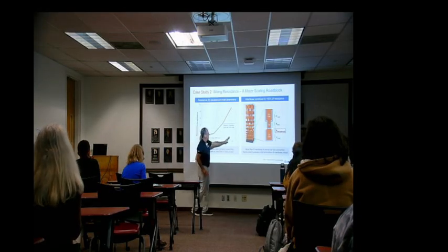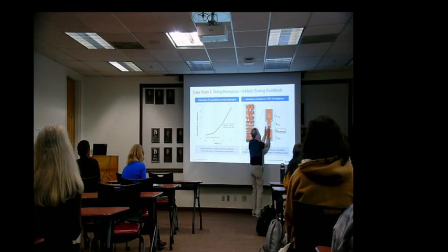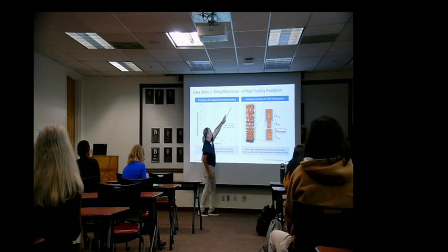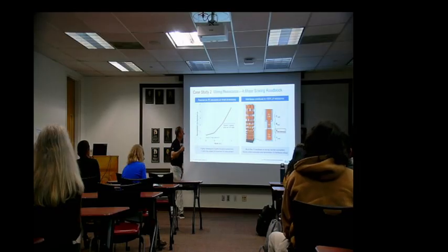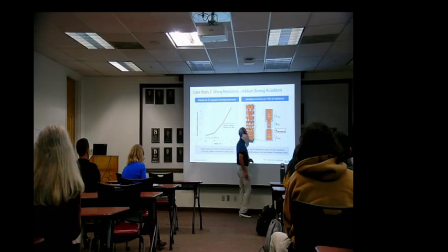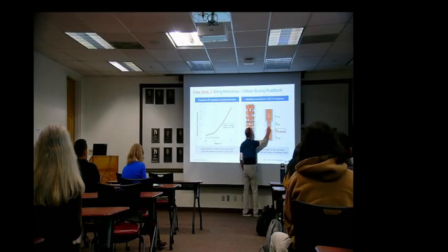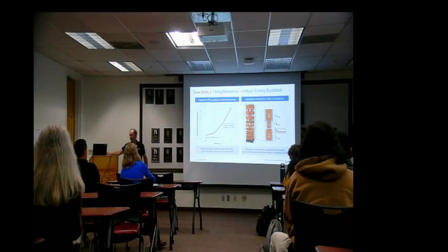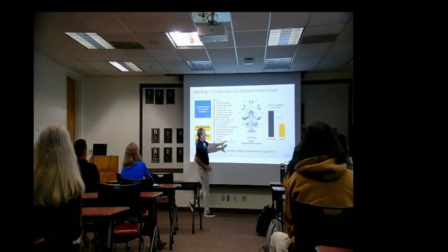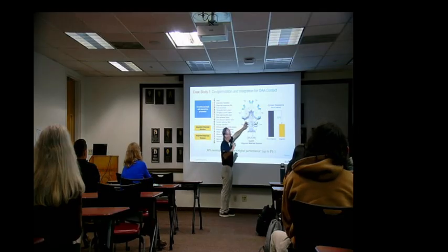So the problem is wiring resistance, and as you go to smaller nodes and the geometry gets smaller, the resistance of the line gets greater. We all know that. But every time this goes up, that means more power, and one of the big challenges we've got is to keep the resistance down. So the interface is what I'm going to talk about here on this tool. It's the resistance between this metal, this copper, and this copper, that interface. So here's a case where we did the etch for cleaning the surface perfectly, followed by epi growth.